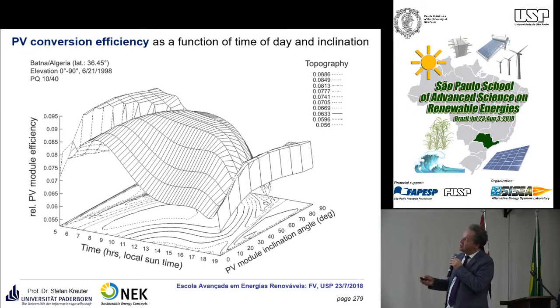This is the time of day, and you see the performance, energy, the PV conversion efficiency during the day. So you see here, morning works quite well because temperatures are low, and then efficiency is dropping significantly because it's a horizontal model, and the heat cannot escape from the backside, so efficiency is really low in the afternoon. If you incline the model a bit, for example, by 30 degrees, you see that immediately the heat can escape from the backside because there is a heat flow, and therefore efficiency goes up.